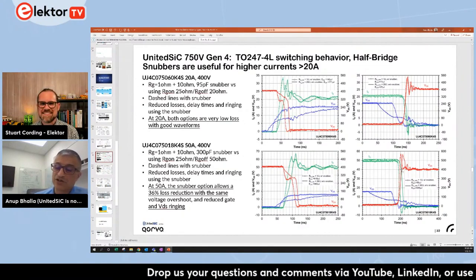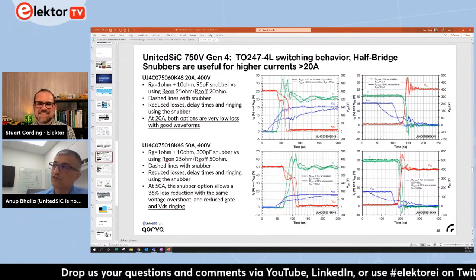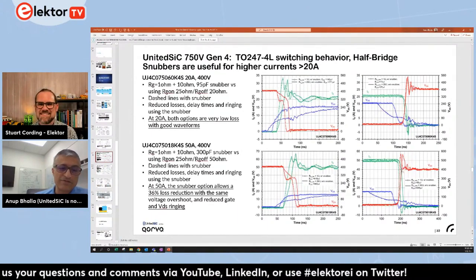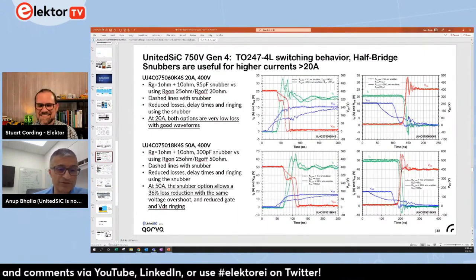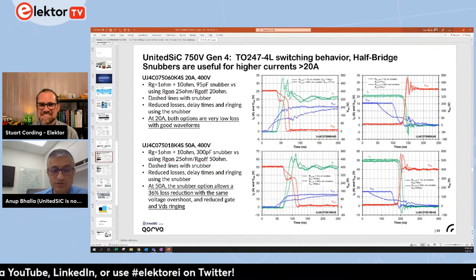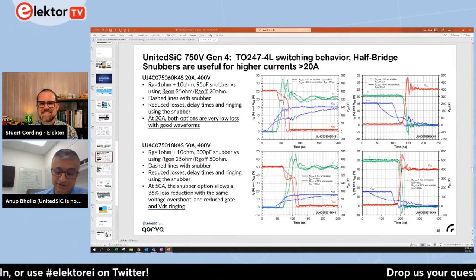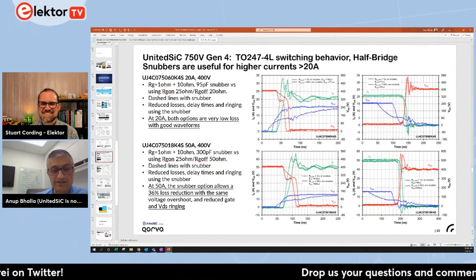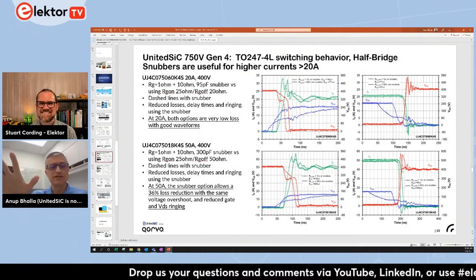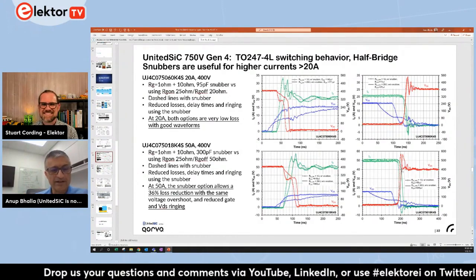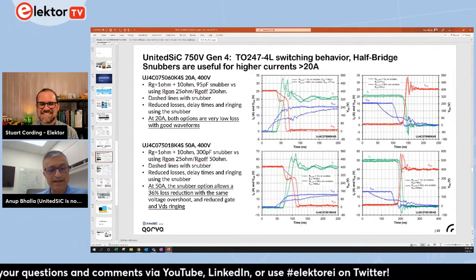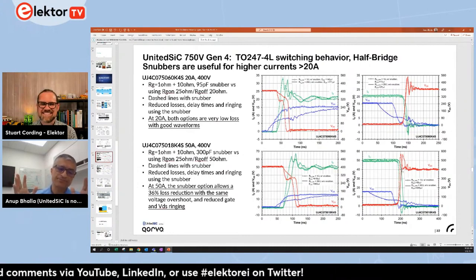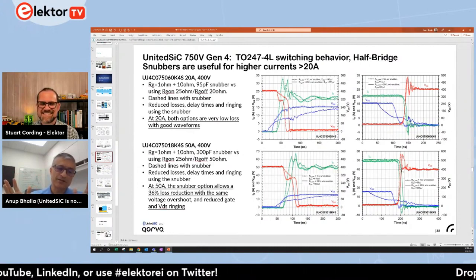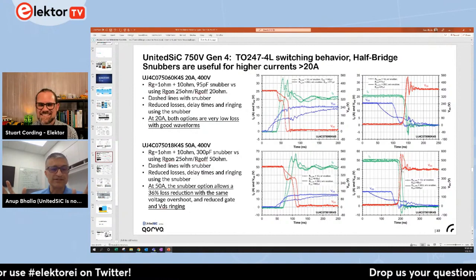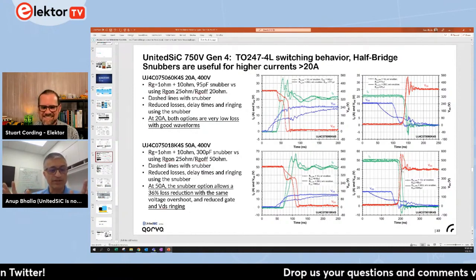Yeah. Then after that, it's got to go to the fab, and in the wafer factory, if you look at a silicon carbide wafer fab, it looks just like a silicon wafer fab for the most part. It just has a few extra tools in it to assist with the fact that you've got to implant at high temperatures, you've got to anneal those implants at a very high temperature, but overall, it looks quite a lot like a silicon line. Might have a few specialized tools at the back end of it. Ultimately, some of the process steps in silicon carbide are lower in throughput than silicon, and therefore the wafers tend to cost more for that reason.